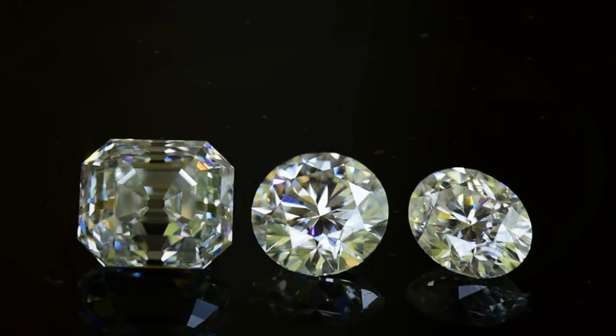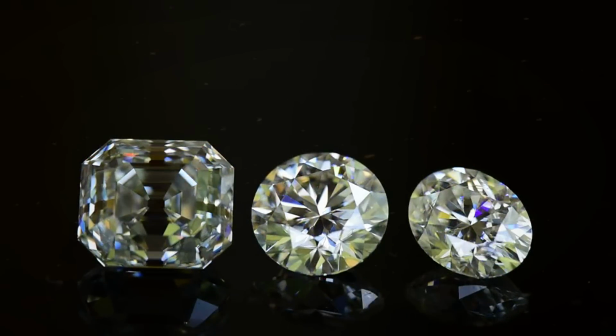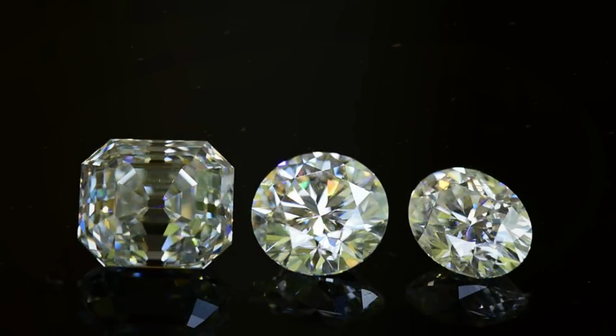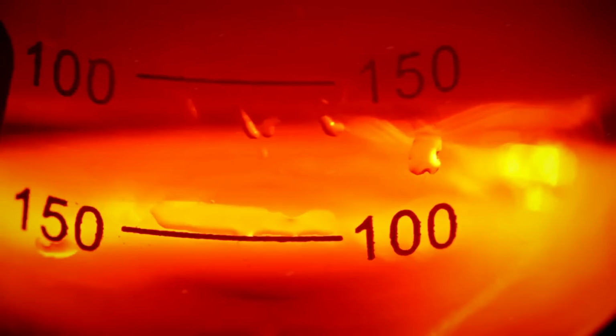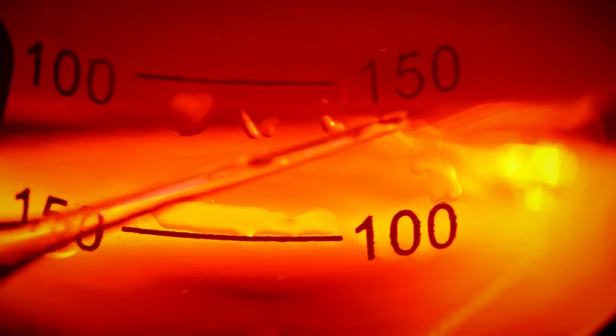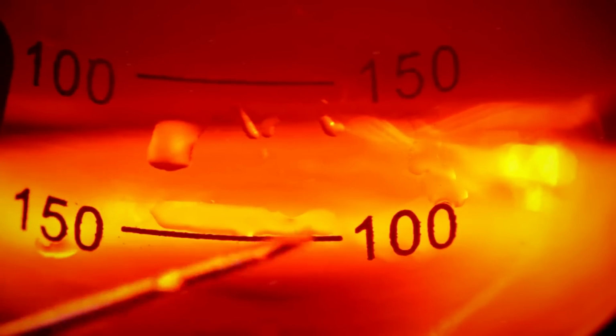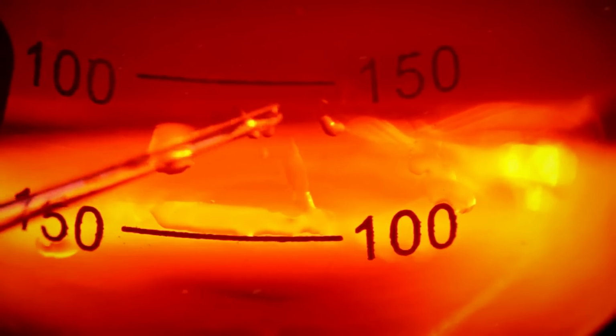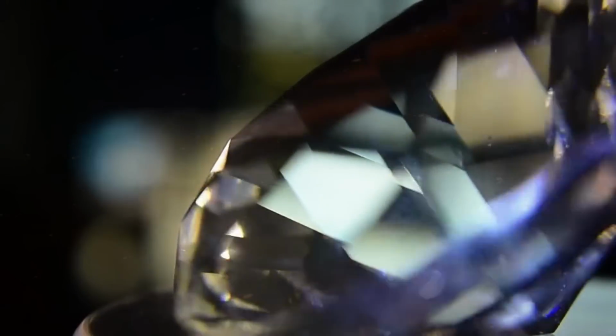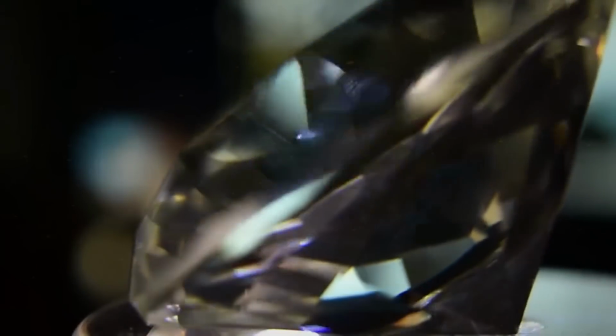Originally a rare mineral discovered in meteorite impact sites, synthetic moissanite is now commercially produced and widely available. Its hardness is high, around 9.25 on the Mohs scale, and its thermal conductivity is comparable to diamond, making it notoriously difficult to distinguish using only a heat probe. But there's a flaw in its disguise.